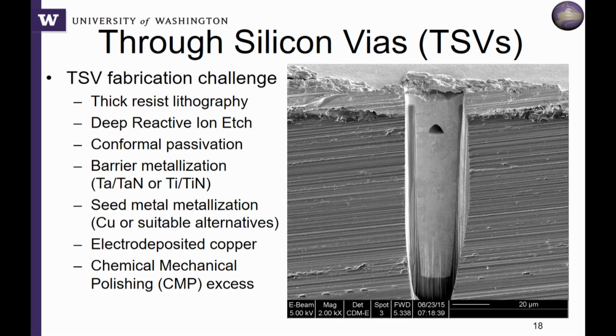After we do all that and get through plating, which is the easy step, we then have to take the excess material off, and we use a chemical mechanical polish to cap those. Then after that, we do the post-processing where we distribute out those signals. So you can see it's a very complicated thing to do just one aspect of a 3D stack.